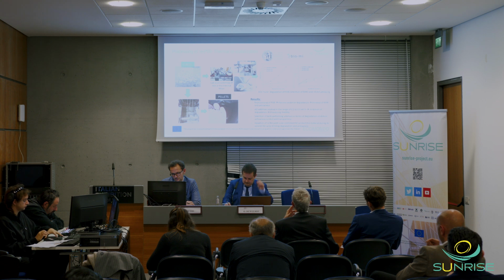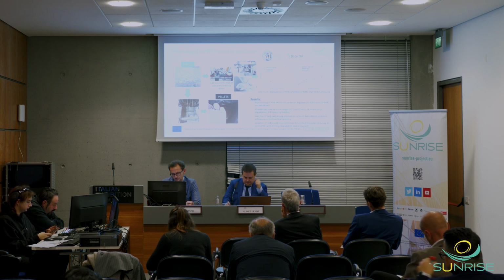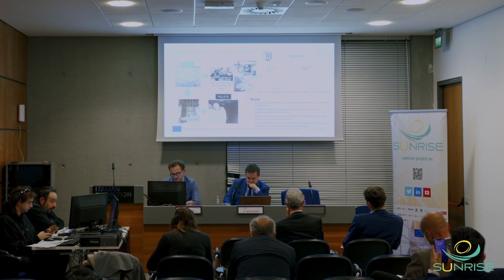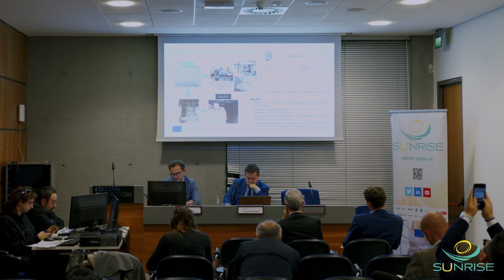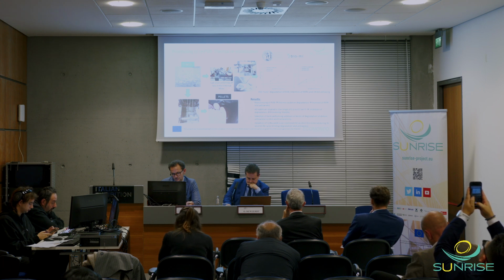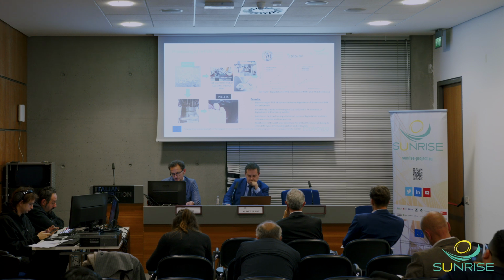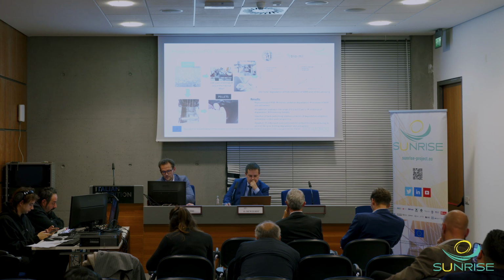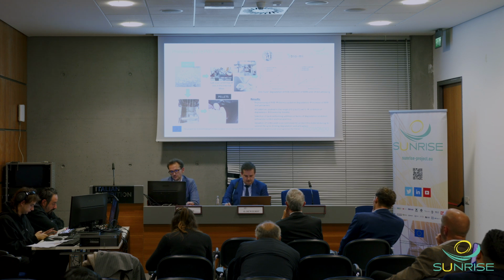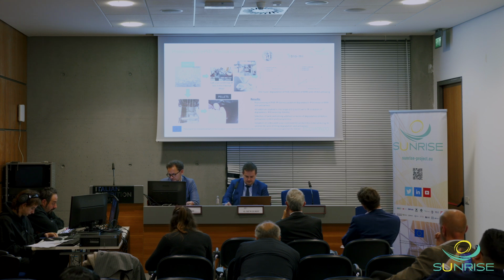Then, as I mentioned, the project needs to transform these flakes into different products for the final applications. The main application the project aims for is the same application, which is a more challenging one because it requires optical quality. In this case, the partners first need to transform these flakes in order to finally obtain an interlayer film for the laminated glass. We have been working on transforming into pellets and also after that into film.